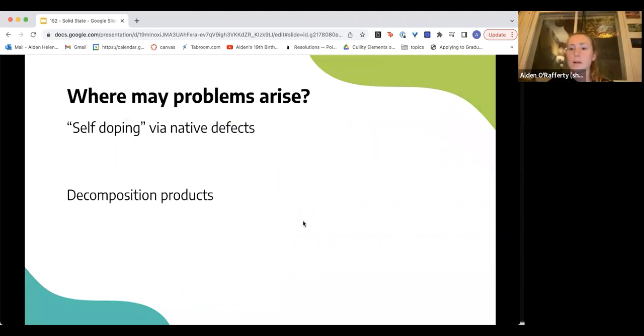And where do problems arise in the context of electrical conductivity? Two things. One, self-doping via native defects, aka the intrinsic or native defects within the material right when you put it in, not a degradation effect, can lead to effects that people call self-doping. So that can make it more conductive than you want, which decreases the performance of your battery. But secondly, you want to be careful about decomposition products. As your battery runs, if it starts to decompose into products that have electrical conductivity, that can lead to hurting your battery's performance slowly, or if there's some sort of electrical conductivity pathway between the anode and cathode, that can short circuit your battery and it'll stop working.